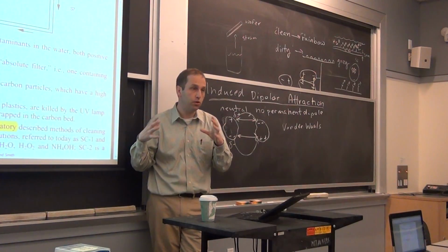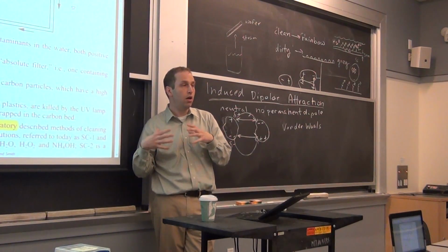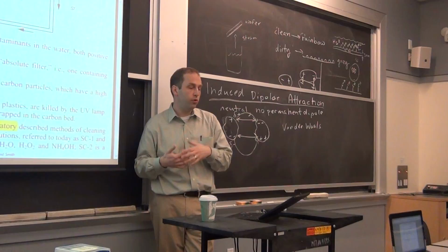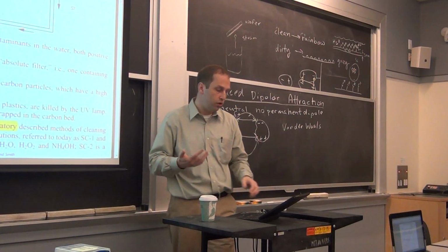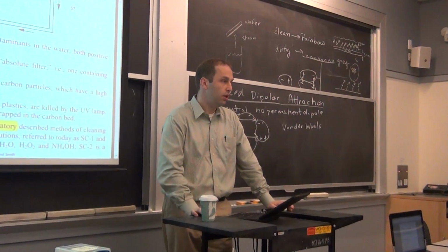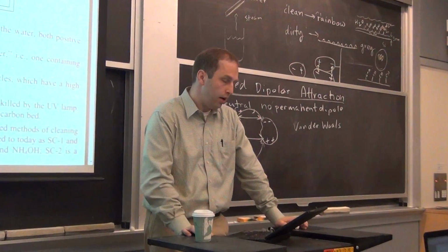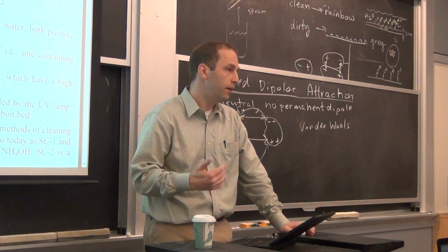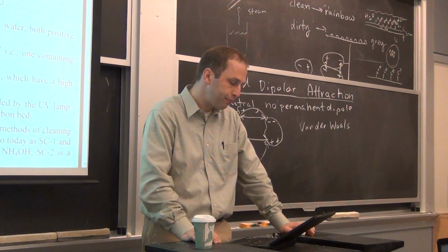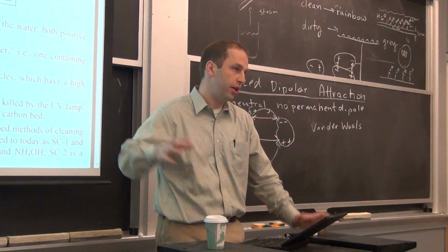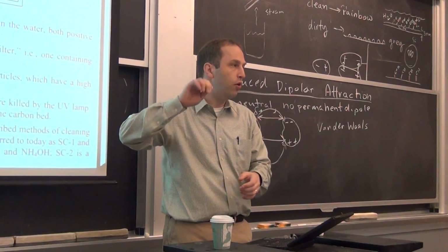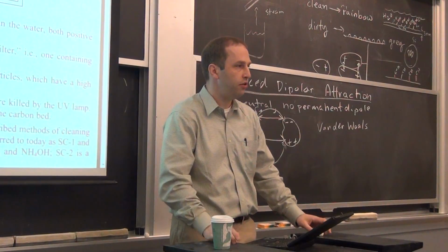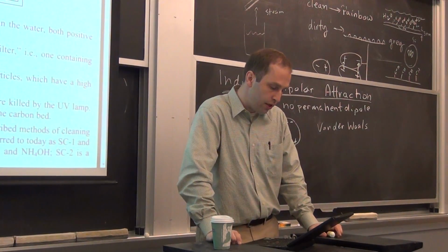Also, the bottles that most bottled nitrogen comes in have a lot of oil in them. So if you are using nitrogen, you should of course use really clean nitrogen, like you would get in the clean rooms here. We use nitrogen that's boiled off from liquid nitrogen. It is very clean. But if you're doing it yourself, you should get a nitrogen dewar and then use the overpressure from the dewar to get your nitrogen rather than using a tank of nitrogen.